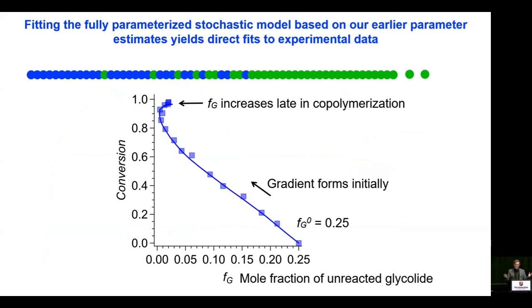So now imagine a copolymerization of lactide and glycolide. We're looking at conversion on the y-axis versus the mole fraction of unreacted glycolide in the monomer feed in the reactor. And so first imagine you're starting there at 0.25 and 0, right down there on the x-axis. The copolymerization proceeds up this conversion curve, and you see that the composition of glycolide is changing, and that's because initially we're forming a gradient early on in the copolymerization. But eventually you'll see that there's this little hook, right, where now the composition of glycolide starts increasing.